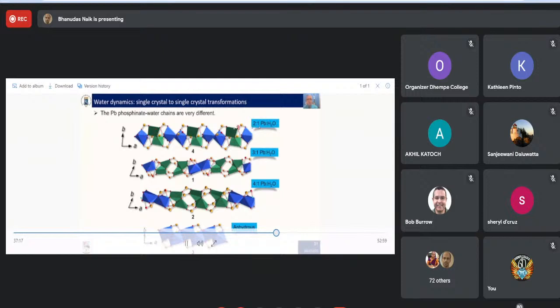So in the 2-to-1, you have the two water molecules go in, and they bridge two lead atoms, and you have the other two lead atoms side to side here. When you're 3-to-1, then you have two sets of two lead atoms and one set of non-water-bridged lead atoms, and it goes like that. It's very interesting.